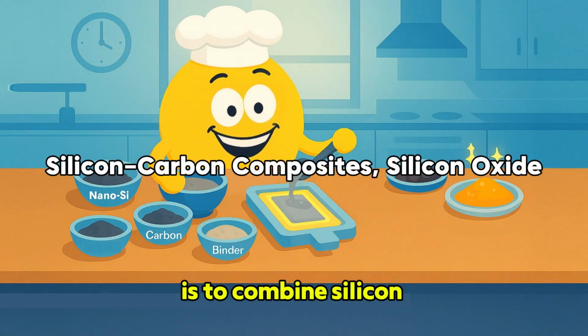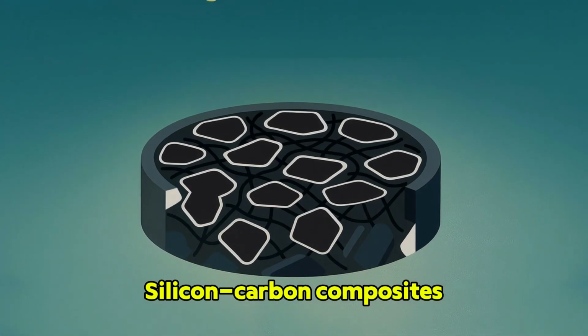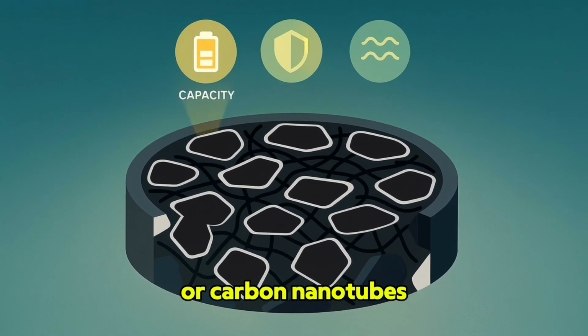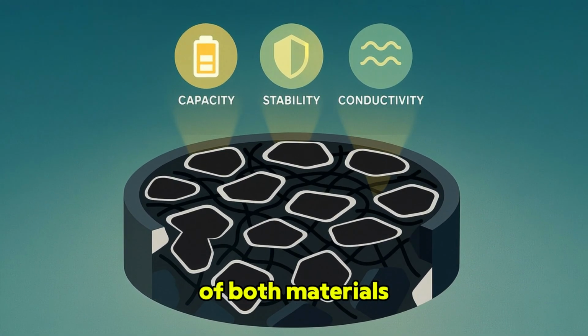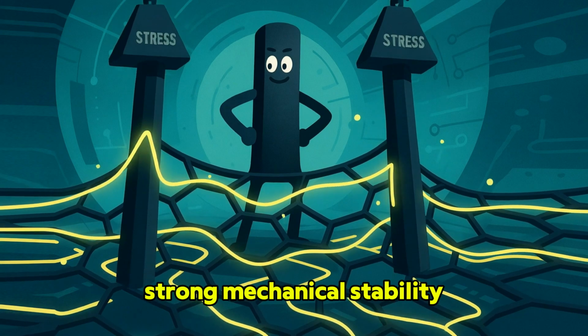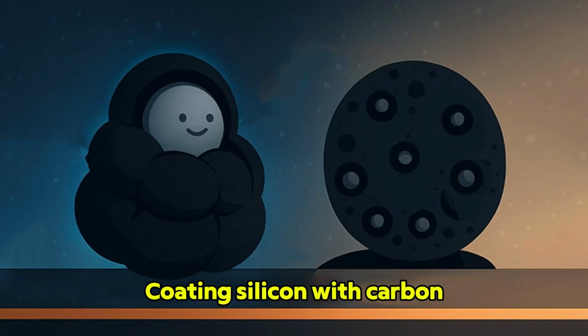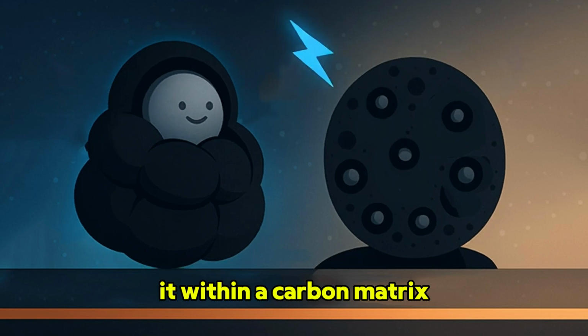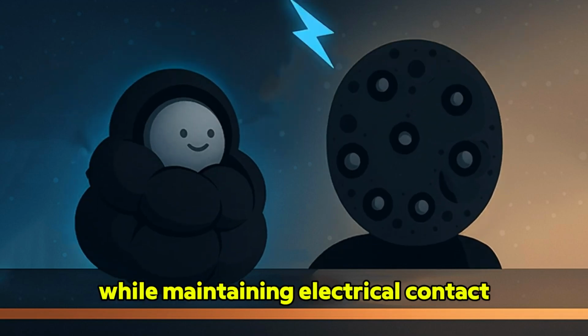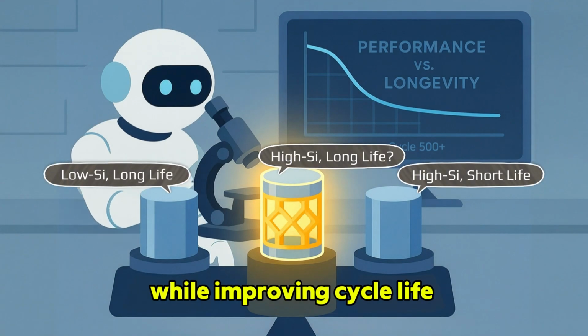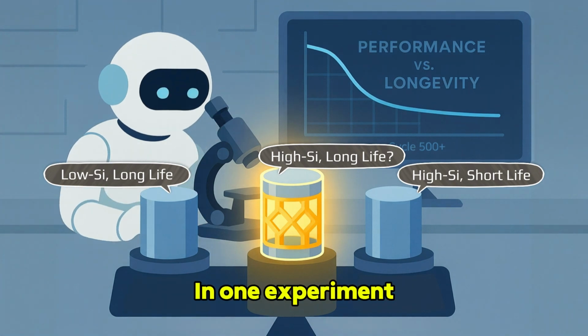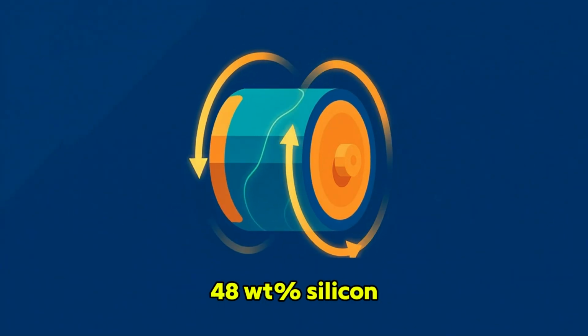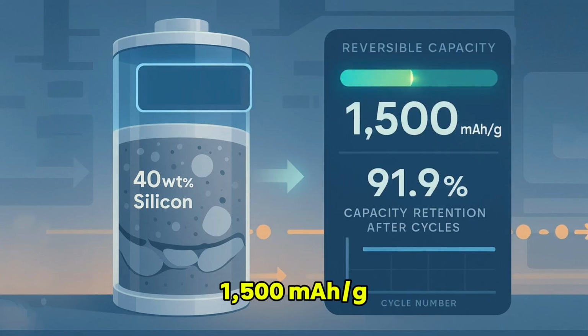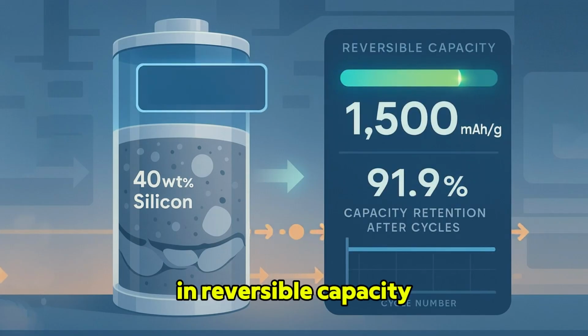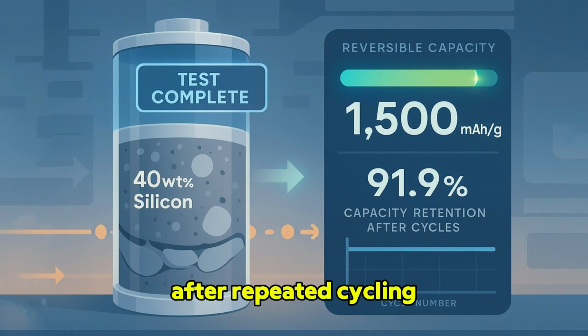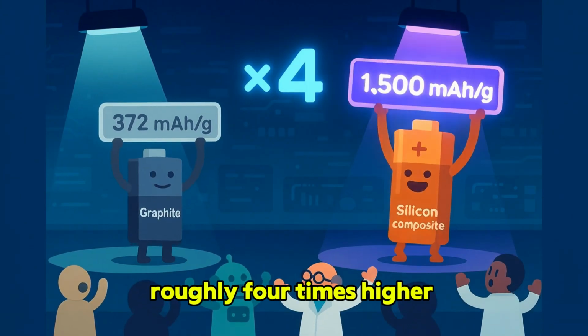The third approach is to combine silicon with other materials. Silicon carbon composites mix silicon with graphite or carbon nanotubes to leverage the strengths of both materials. Carbon provides strong mechanical stability and high electrical conductivity. Coating silicon with carbon or dispersing it within a carbon matrix cushions expansion while maintaining electrical contact. This allows higher silicon content while improving cycle life to a practical level. In one experiment, a composite with about 40% silicon delivered around 1,500 mAh per gram in reversible capacity, meaning about 91.9% stayed usable after repeated cycling, roughly 4 times higher than graphite.